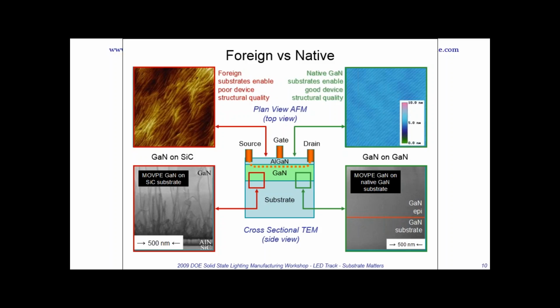And if you go GaN on a GaN substrate, at least in that field of view, you won't see any extended defects. And the top can look really beautiful, and the top cannot look real beautiful for the heteroepitaxy case. And so this kind of logic carries through for all semiconductor materials. I challenge you to tell me one device out there in volume that's not grown on the native substrate.